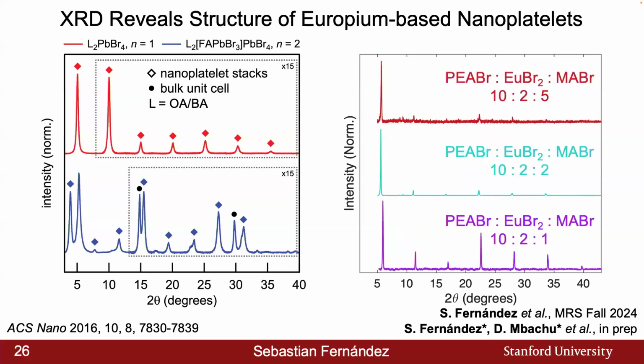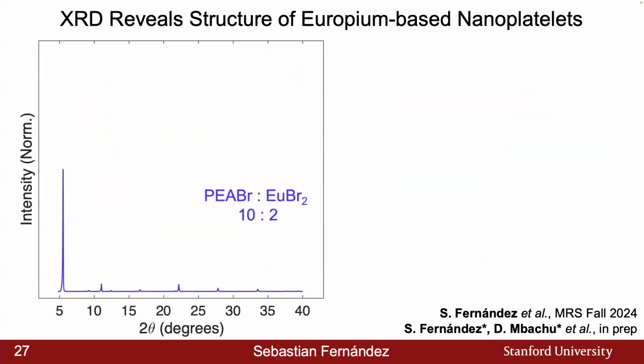In fact, if we look at them with increased methylammonium bromide, we don't really start to see XRD scans that resemble the N=2 case here, which shows an interesting deviation from the previous class of system that we've seen down here. The theory is that the methylammonium bromide is not really contributing to the crystalline structure of this material. And so at this point, we look at forgoing the bulk A cation completely. So this is the 10:2 ratio of phenethylammonium bromide to europium bromide, with the most representative XRD scan that we have.